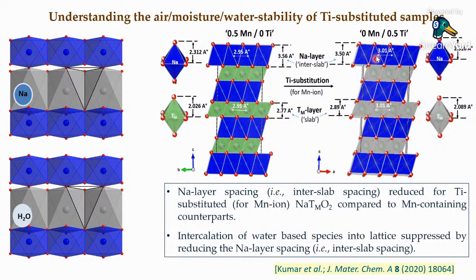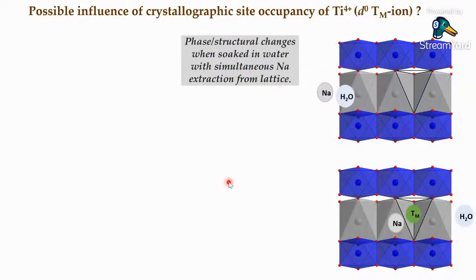Now, this sodium layer spacing is sometimes also known as inter-slab spacing, because these are referred to as transition metal oxide slabs. So when this spacing got shrunk, it caused hindrance to the insertion of the water-based species, and that rendered it water stable to some extent.